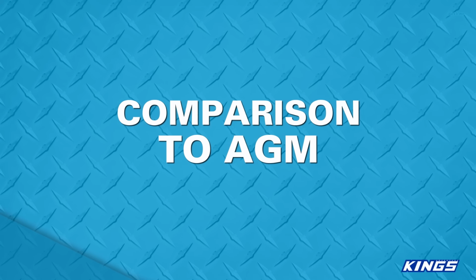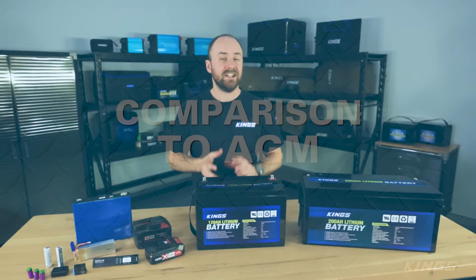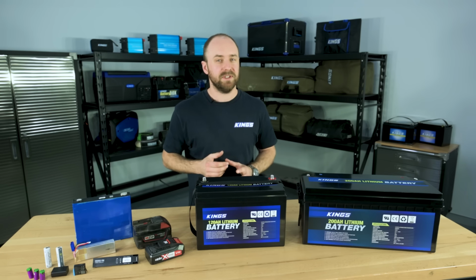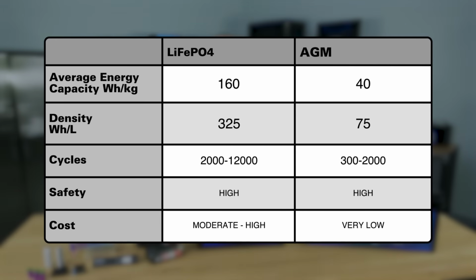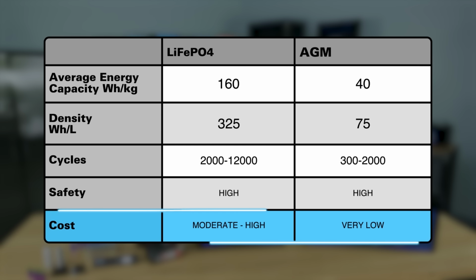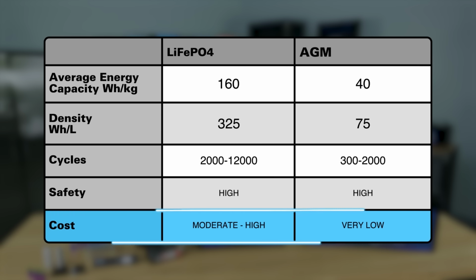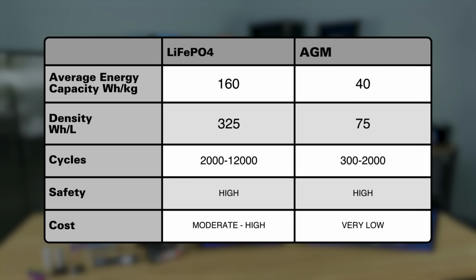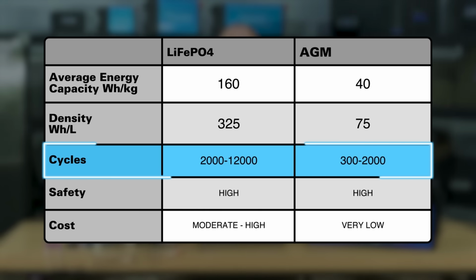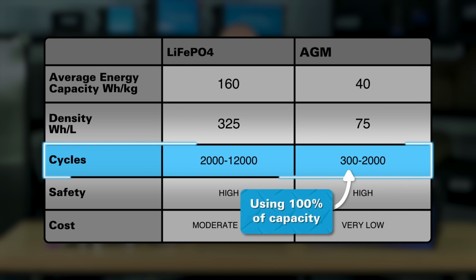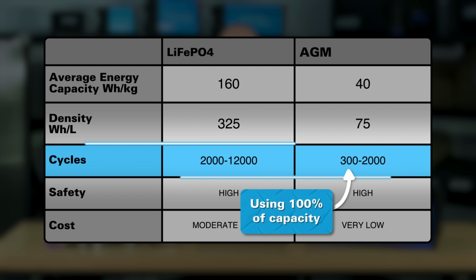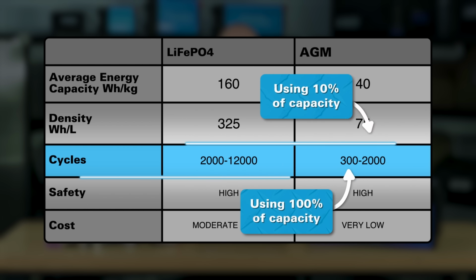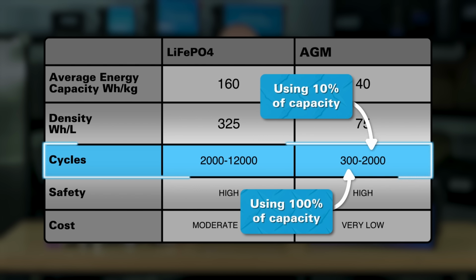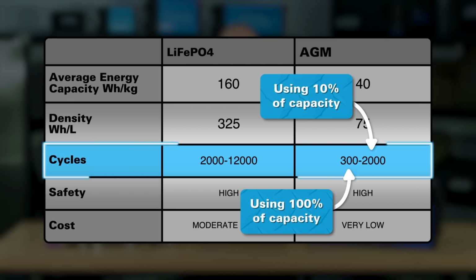Let's now take that last column for lithium iron phosphate and compare it to the currently most commonly used camping battery, the AGM. Yes, a lithium iron phosphate might cost 3 times more than a lead acid AGM, but let me talk you through how they compare over the life of a battery. With an AGM, the further you discharge your battery, the less cycles you get. Discharging all the way to 0% would mean about 300 cycles. Conversely, discharging only the top 10% of the battery down to 90% full capacity may net you around 2,000 cycles.